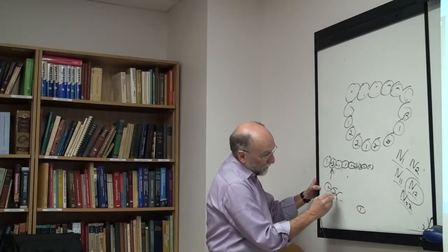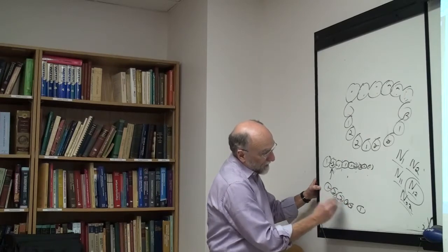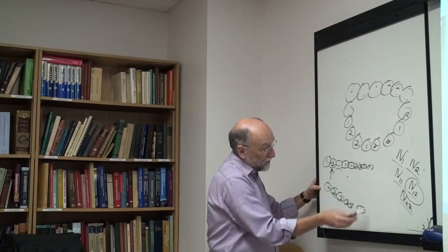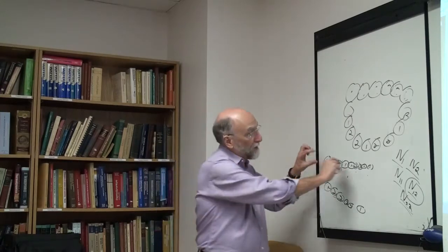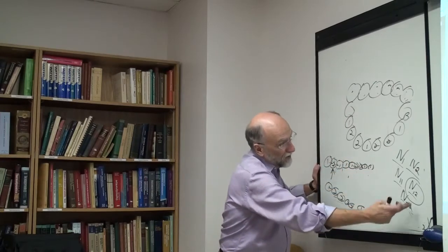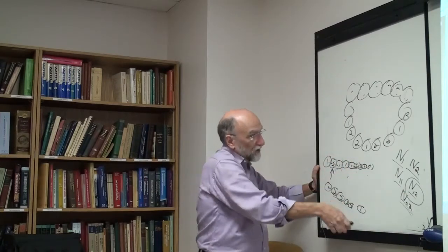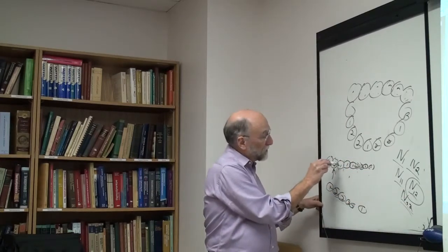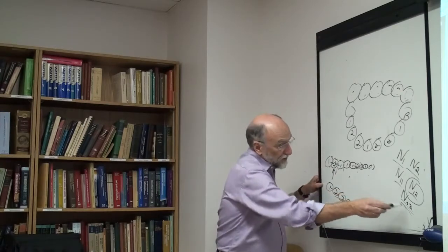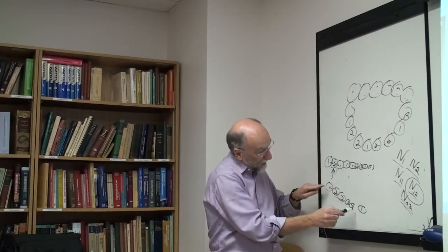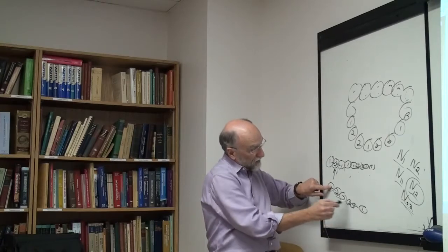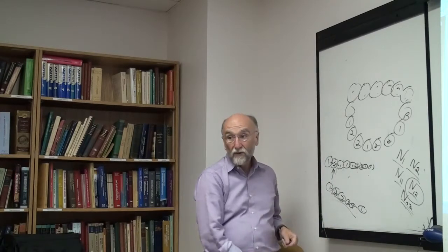Now I just move the 1 over and I put a bunch of 2s in here, randomly distributed with all these other 2s until I have the right number of 2-2 pairs. So you can read it and see what you're doing. You line up all the 1s, you shove in the right number of 2s in order to give the right number of 1-2 pairs, and then you put the rest of the 2s in beside the 2s that are already there. That doesn't change the number of 1-2 pairs, but the 2s are then what you want.